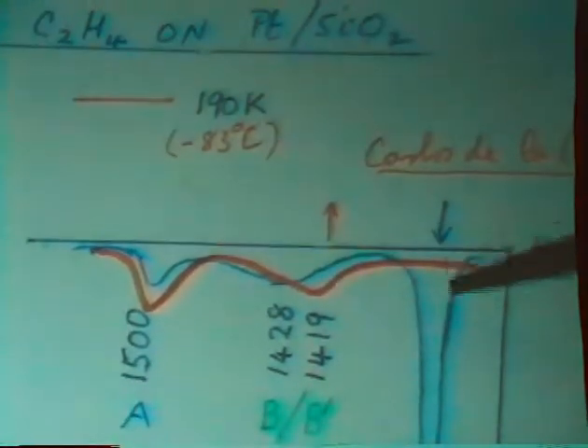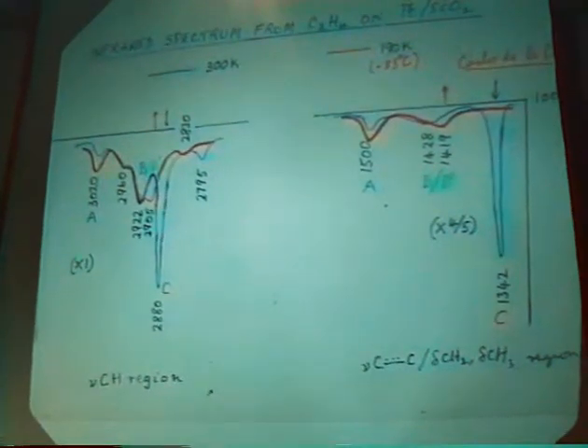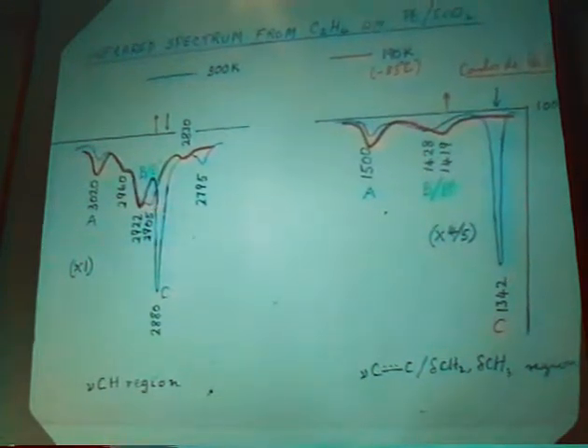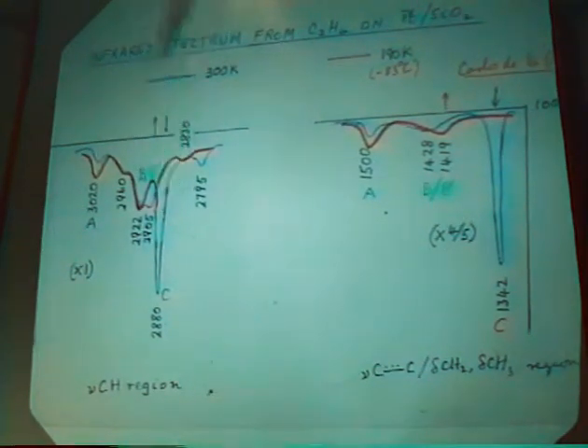So at low temperatures, we don't get any of the ethylidyne species. But what happens is that at a better resolution, we've split this single band into two. And one component of this, as we raise the temperature to room temperature from, whatever it is, 190K, one of the components goes way down, and up comes the ethylidyne. So we're seeing what Ibach had proposed, a transition from di-sigma to ethylidyne, actually on the finely divided metal catalyst as well.